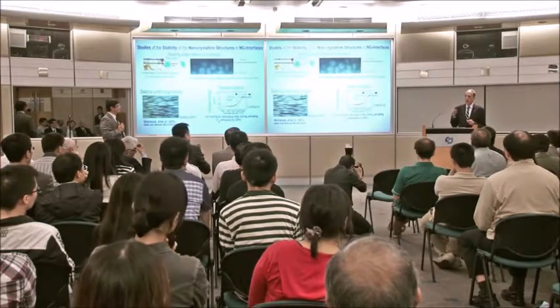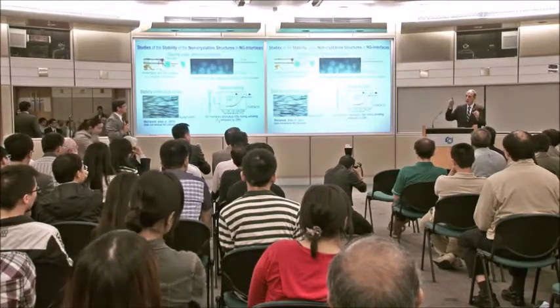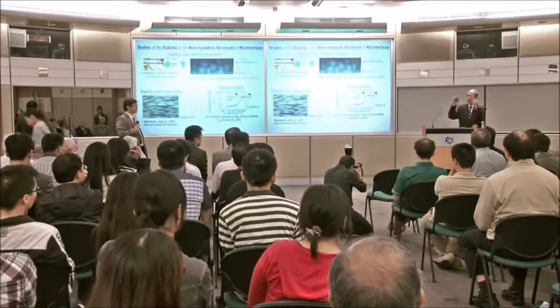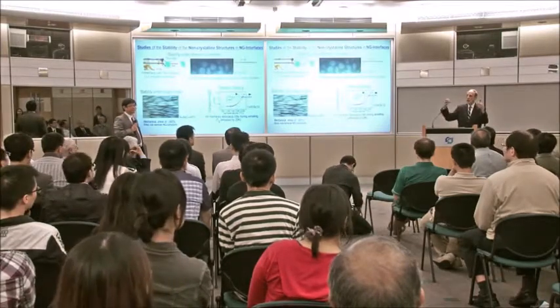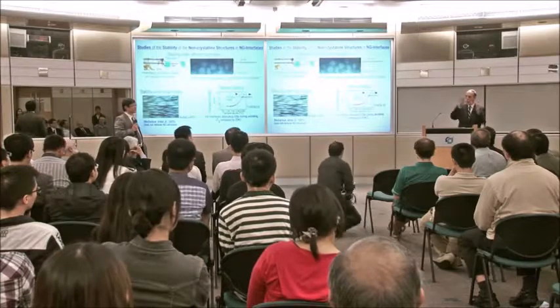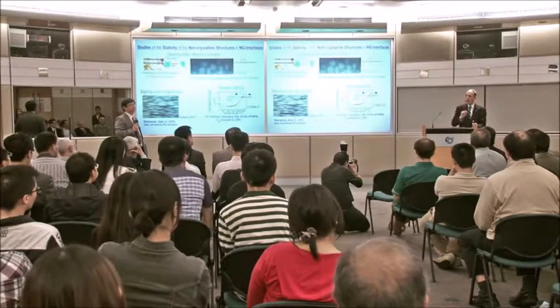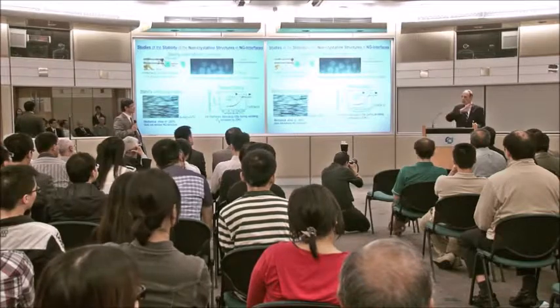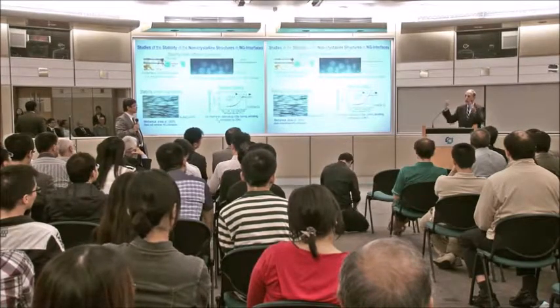No, it's the interface. What we do is we first produce the clusters and isolate them from one another by putting an argon layer on the surface so the clusters cannot see each other. So they are isolated clusters, isolated by argon. Then we do the Mössbauer spectrum, and we get a very normal Mössbauer spectrum. Then we pump the argon off, and the clusters see each other, and at that moment we see the changed spectrum. So without any external pressure, as soon as the interface forms, it drops into that deep free energy gap and it remains there. And when we push things together, we get more interface, but we don't change the structure. Okay.